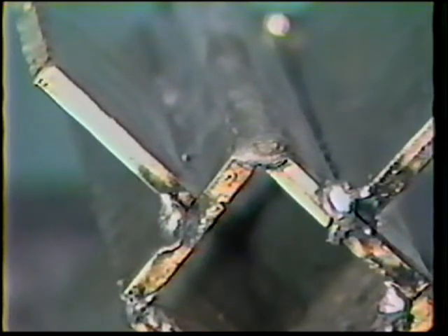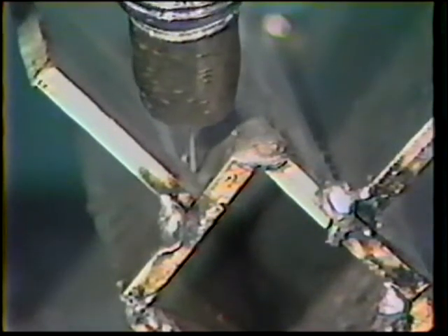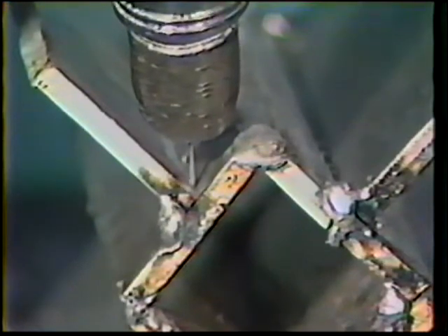To weld the T-joint, place a cooled workpiece on the table so that one of the T-joints is in the flat position. Position the gun at the end of the joint with a 45-degree work angle and a 20 to 30-degree push travel angle, centering the wire in the joint. Move along evenly, keeping the wire centered in the joint. Use a very slight weaving motion to fill the joint evenly. The finished bead face should be 3/8 inch wide, flat or slightly convex, and reasonably smooth and regular.